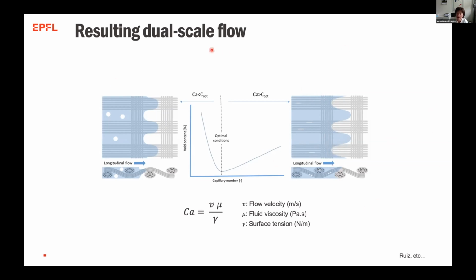And a very interesting result that was found is about the void content in the final part that you cure and demold. If you go super low and let the capillary forces do their job, you will entrap a lot of porosity in between the toes. Whereas if you go super fast, you will not entrap porosity in between the toes, but you will entrap porosity in the bundles. So it was found that the void content, around a certain capillary number which is the optimal one, will increase a lot if I go too slow, and a bit less if I go too fast, because of course it's in the toes.